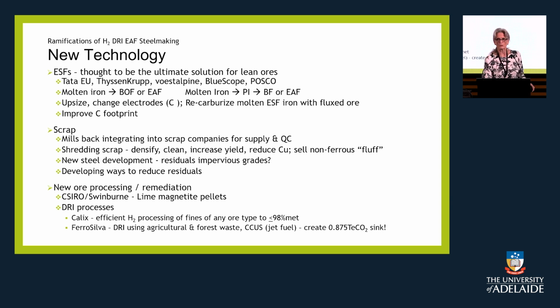Scrap mills are back-integrating into scrap ownership to ensure quality control and the supply moving forward. Shredding scrap has been shown in the UK to densify the material and clean it up, to 98% yield from about 89%, which is quite significant. They also managed to reduce the copper contained within the scrap, which became a significant improvement. They also found that there was a substantial sales value for the fluff coming out of the shredder because of its non-ferrous content.